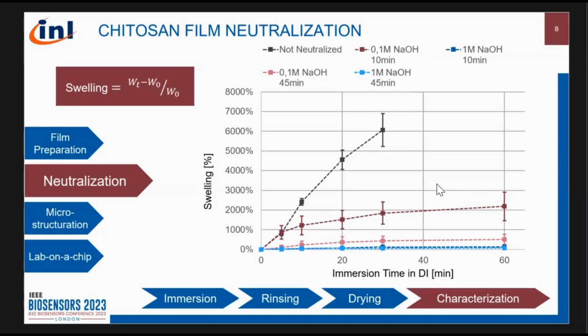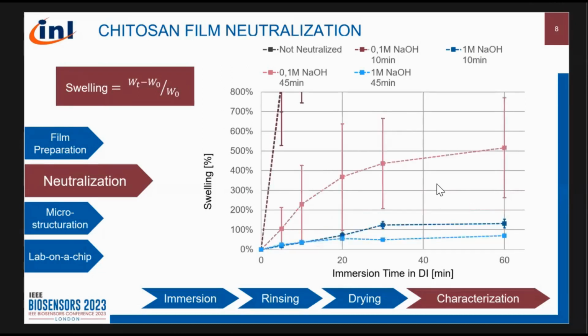So firstly, you see the highest swelling rate is for films that are not neutralized. And after 30 minutes in water, they even start to dissolve. So we have no points further. And you can see more clearly, if I zoom in here, that depending on the concentration of sodium hydroxide and the time spent, if we increase both the concentration and the time spent in the solution, we will decrease the swelling, which we want. We want to have as low swelling as possible.